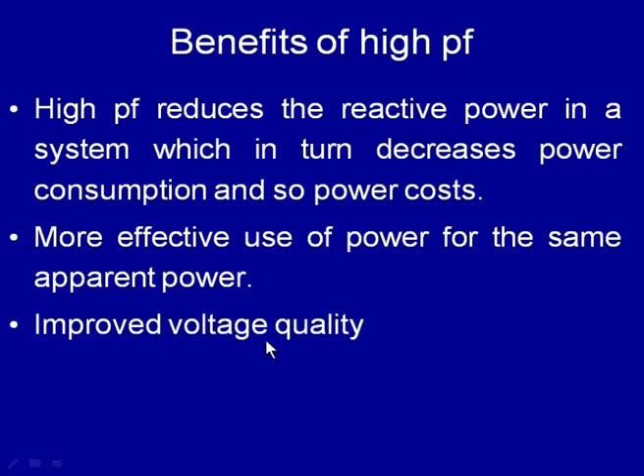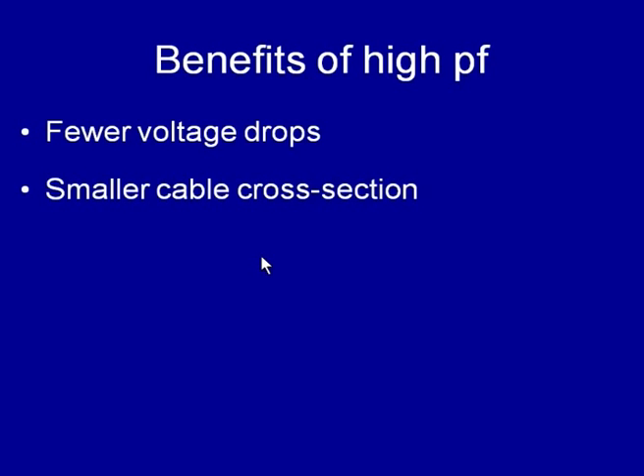Further, it also helps in getting improved voltage quality. So, it is good to have a higher power factor of the welding power source, but when it is required that the current and the voltage are out of phase, the lower power factor is intentionally used in welding power sources, so that the arc can be reignited, especially if it is extinguished when the current is 0 when using AC welding. There are a few other benefits of the high power factor, like fewer voltage drops, and smaller cables can be used. The cables having a smaller diameter cross section can be used for drawing the current, and the transmission losses are also reduced. So, all these things are in favor of reducing the investment as well as the consumption of power while using the high power factor.